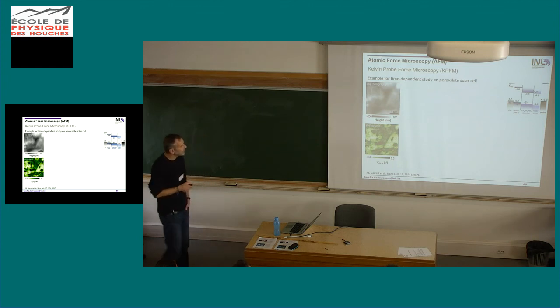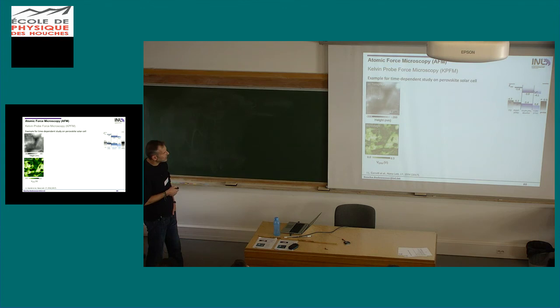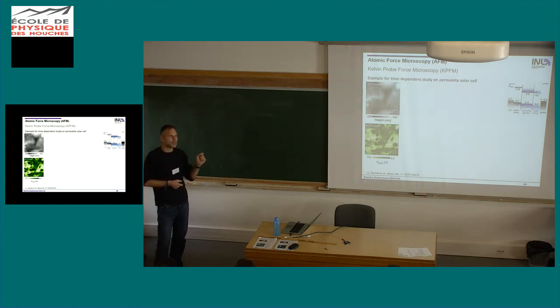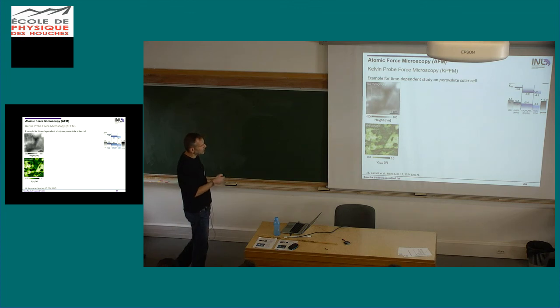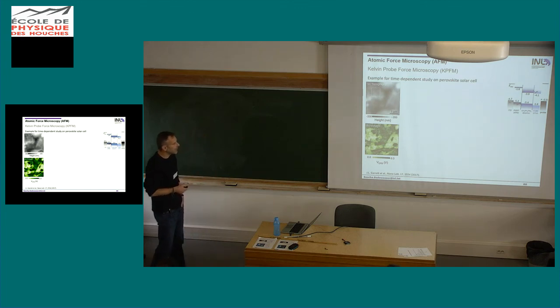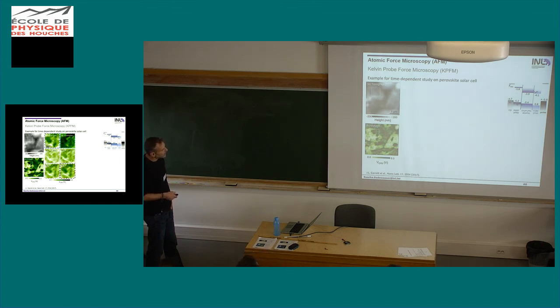So here it's a study on a perovskite material. This is the perovskite surface. So they measured the topography with Kelvin probe force microscopy, and it's a special mode of Kelvin probe force microscopy that allows scanning very fast. Normally you take, let's say, half an hour to an hour for one image. Due to the method they used, they can measure one image in 16 seconds. And this allows, of course, then to look at dynamics in the sample on that time scale. So they get this kind of pattern in the CPD image, and then they only looked at what happens here.